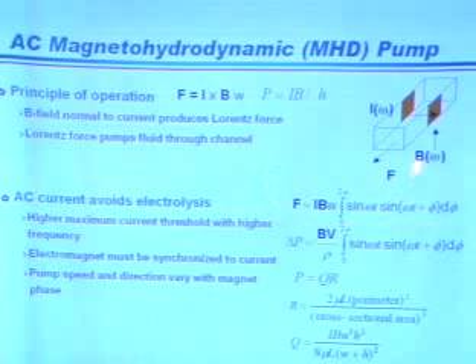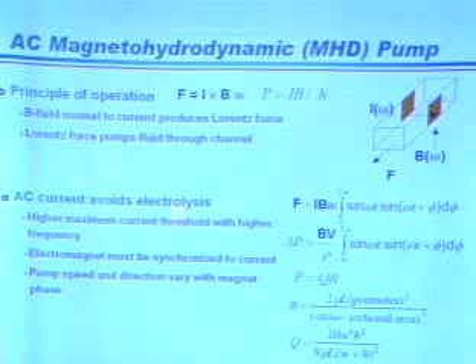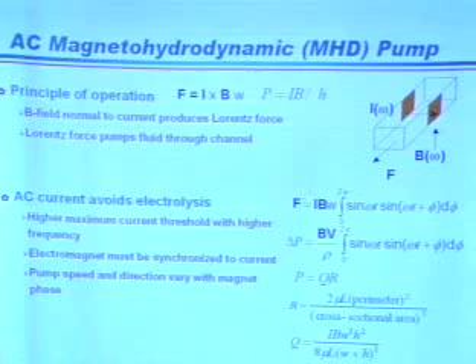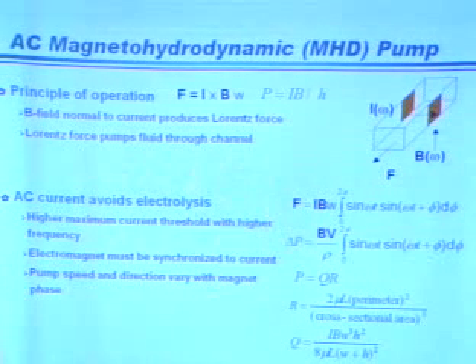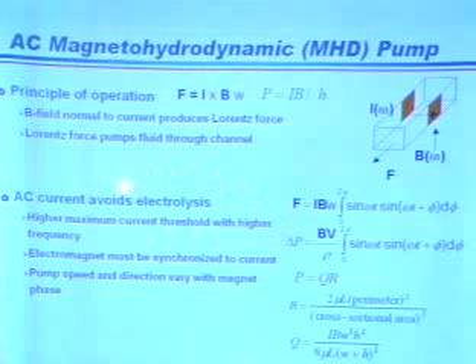The problem for a direct DC field arrangement is that you easily generate electrolysis, because at about 1.2 volts, theoretically, you start having bubbles generated in most ionic water concentrations. And so AC current actually allows you to bypass that. If you reverse and synchronize these two fields fast enough, then you don't allow enough time for the bubbles to reach the critical threshold. So there's a frequency limitation, of course.